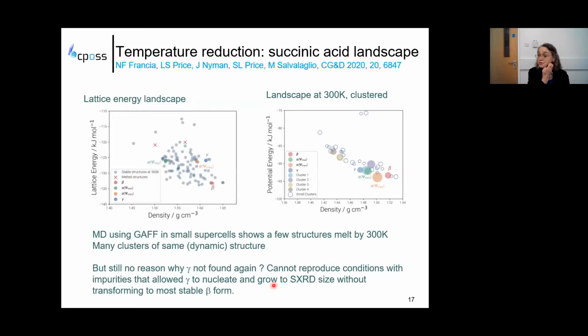And this is one of the theoretical things that we've been working on with Matteo Salvaggio, a student in chemical engineering, doing molecular dynamics. For the succinic acid CSP, some of them melt, and also seeing how he could show that a lot of the structures can merge to the same thing. However, this did not explain why that gamma crystal formed. It still looks like a perfectly good, stable structure at normal temperatures in this dynamically moving model there.